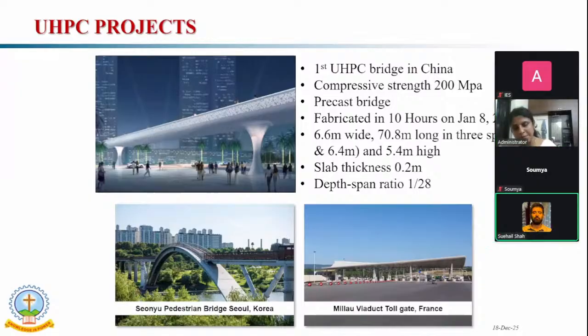Then if you are considering UHPC projects, the first UHPC bridge is in China with a compressive strength of 200 MPa. It is a bridge 6.6 meter wide, 70.8 meter long, and 5.4 meter height. The slab thickness is 0.2 meter. The depth to span ratio is only 1/28.